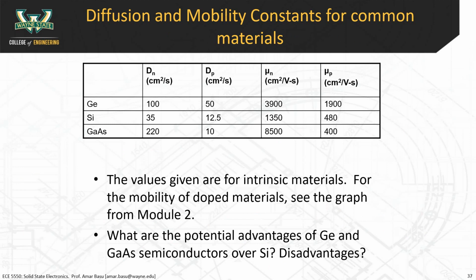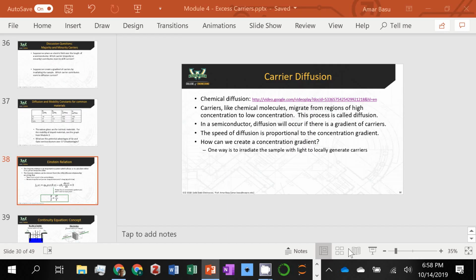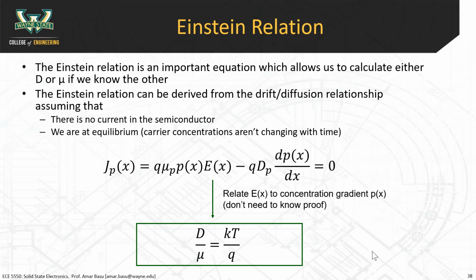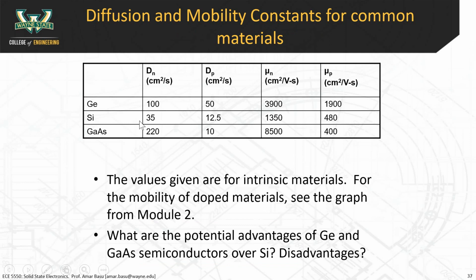So here are our diffusion and mobility constants for the three most common semiconductor materials: germanium, silicon, and gallium arsenide. Silicon is obviously by far the most common. So silicon has these diffusion coefficients, 35 and 12, for electrons and holes. The units for diffusion coefficient are centimeters squared per second. And the mobilities for silicon are 1350 and 480. This is for low doping concentrations. Normally on an exam, if I give you these constants, remember that they assume low doping.